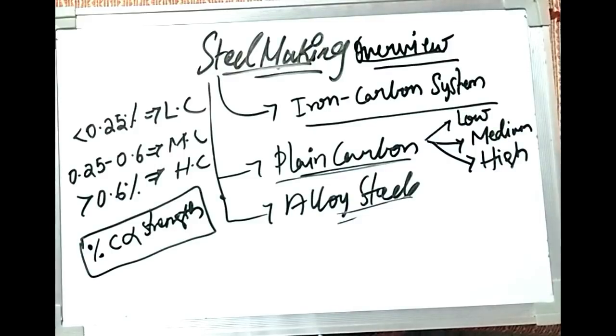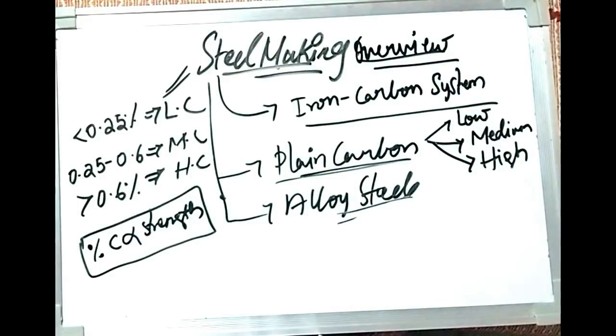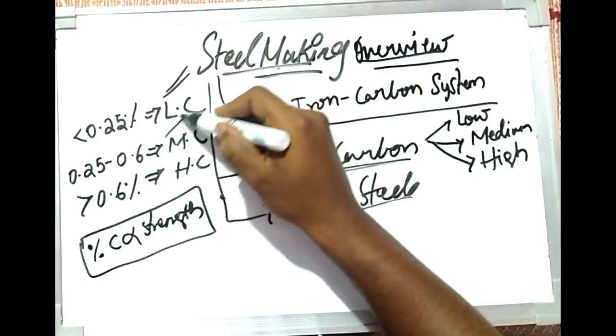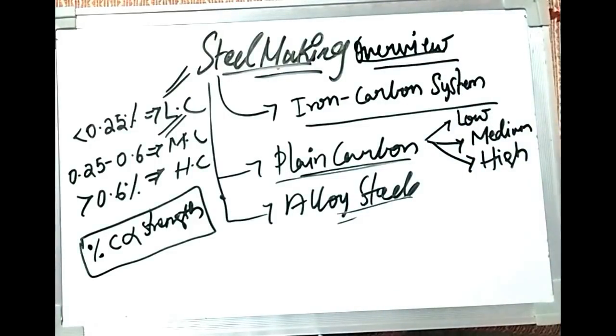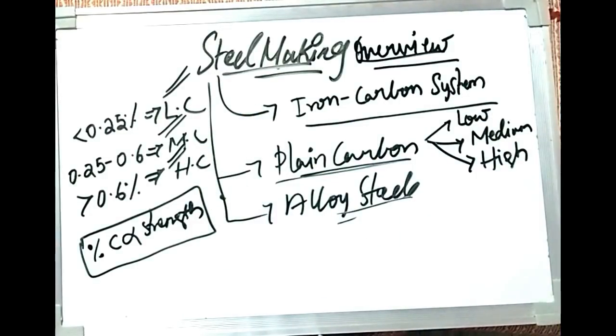Common products like nuts, bolts, and sheets which don't require much strength are made from low carbon steels. For somewhat higher strength applications like machinery, automobile parts, and agricultural parts like gears and axles, medium carbon steels are used. High carbon steels are the strongest and hardest — they are used in cutting tools and musical wire strings because of their strength, hardness, and wear resistance.